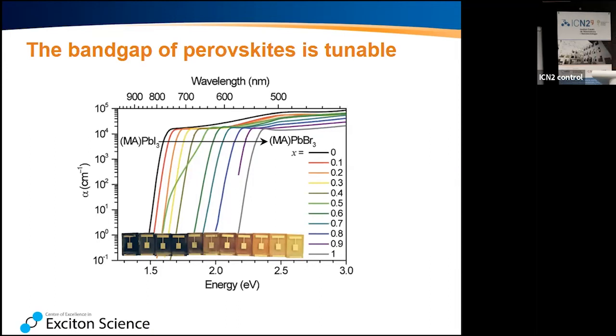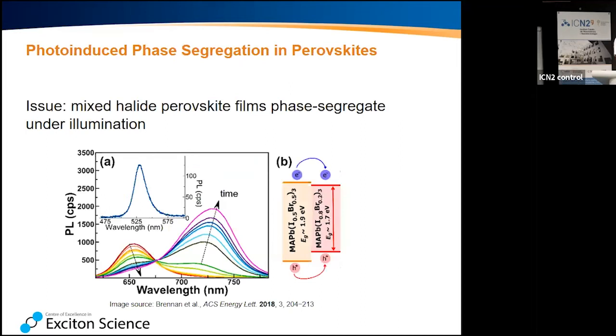The problem is, and that's also very important for making tandem solar cells, because for a tandem solar cell, typically 1.5 is not ideal. You would much rather want something that is in the range of about 1.7. So that's where this halide tunability is very, very useful. Now, the problem is if you shine light onto, for example, a bromide-rich perovskite, so that we start off with a red line here, and as we shine light on it, we see this fluorescence peak of our bromide-rich material disappear. And instead, we actually see the luminescence of an iodide-rich phase.